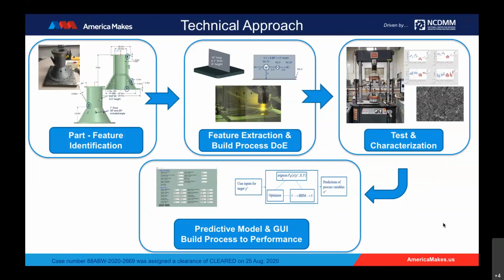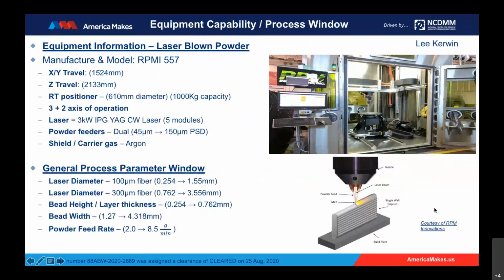Next slide. What I failed to tell you in the beginning was that the DED process of interest is a laser blown powder process, primarily made by RPMI, and it was the 557. The facility that we used was at EWI in Buffalo, New York. And here are the process capabilities for that equipment set. The powder that we were using in this particular program was Ti-6Al-4V, and it was a powder set about 50 to 150 microns in diameter.